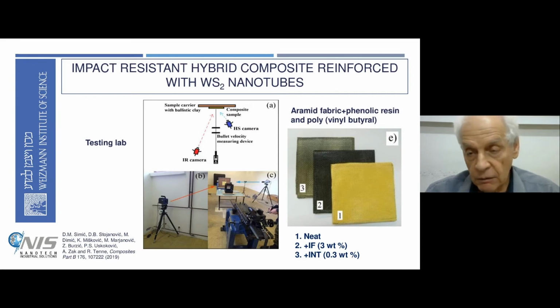They used aramid fiber to make a fabric. This is the neat aramid fabric, which is yellow, and then they added nanotubes, up to 0.3%. You see that they added the nanotubes, and not much - you don't need more than 0.5% or 1%.